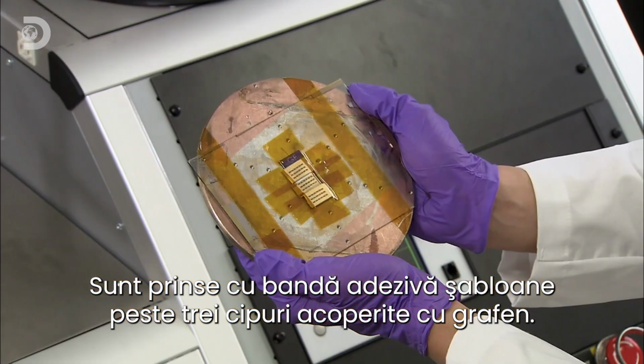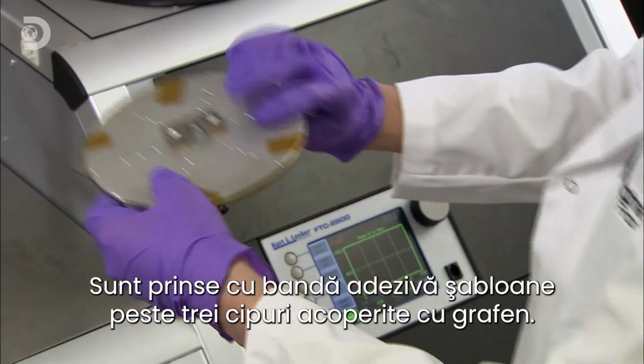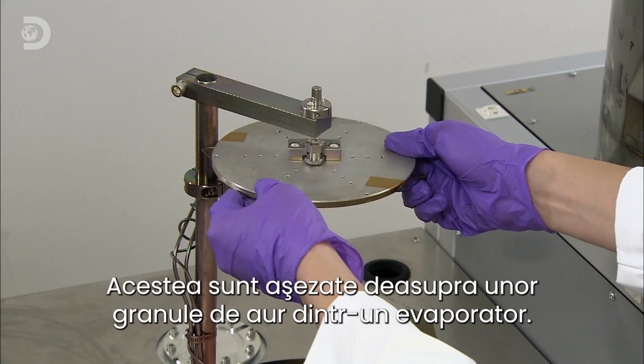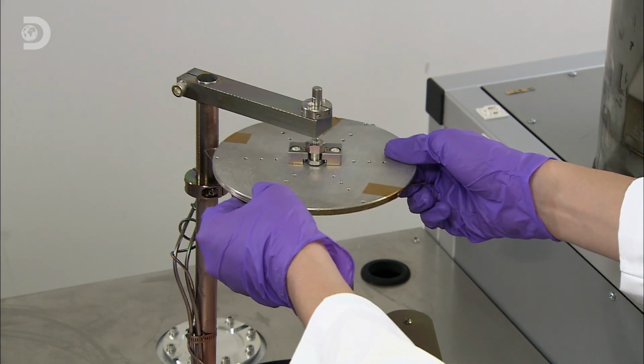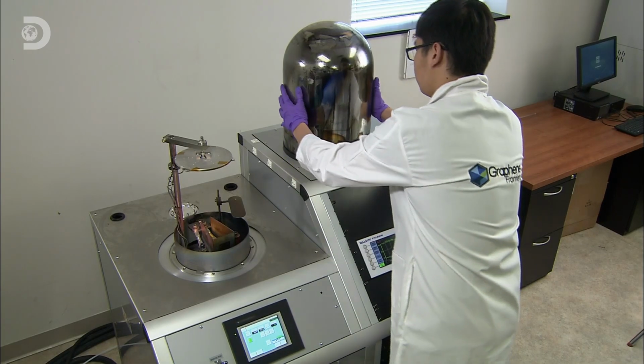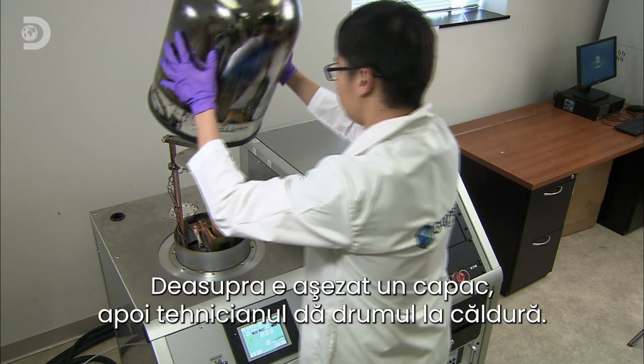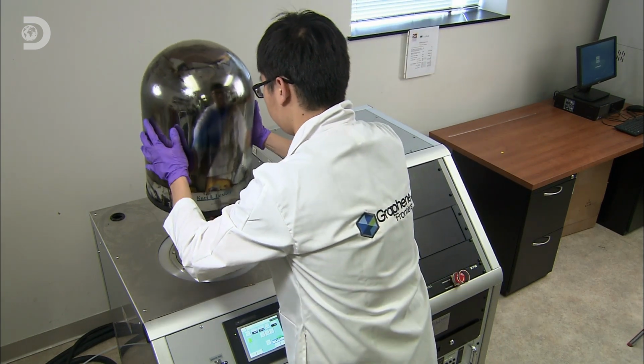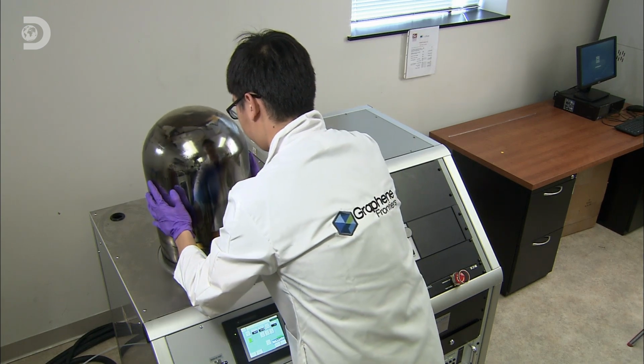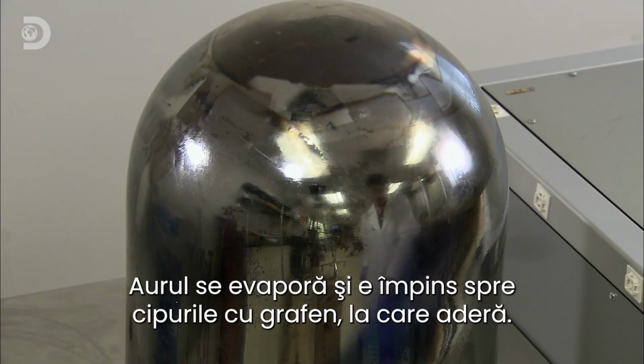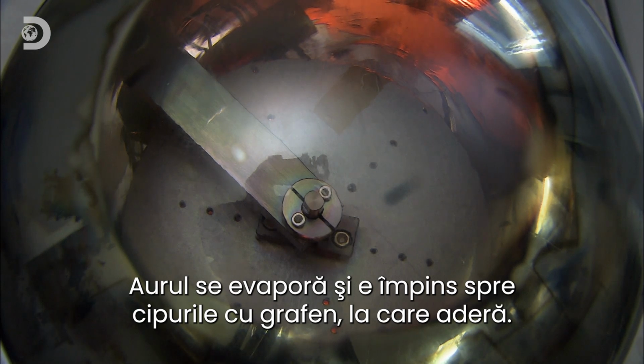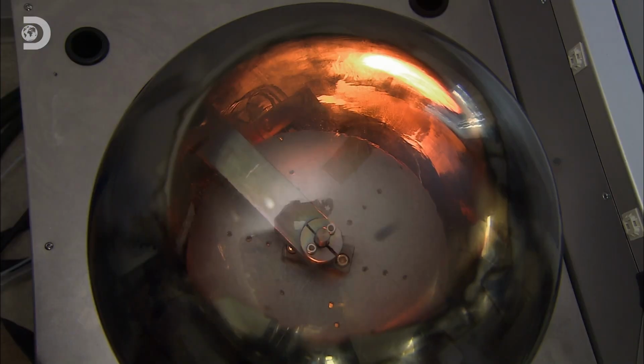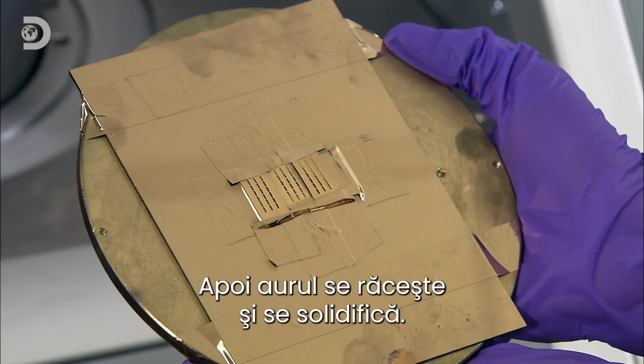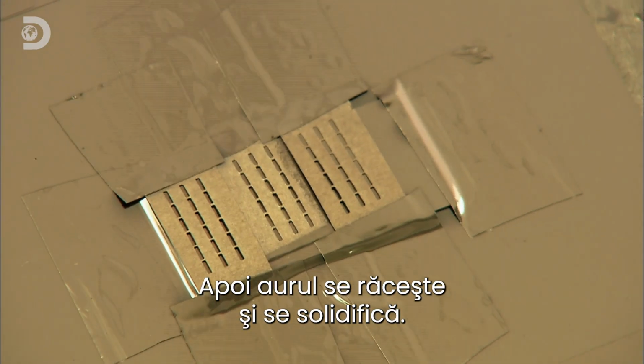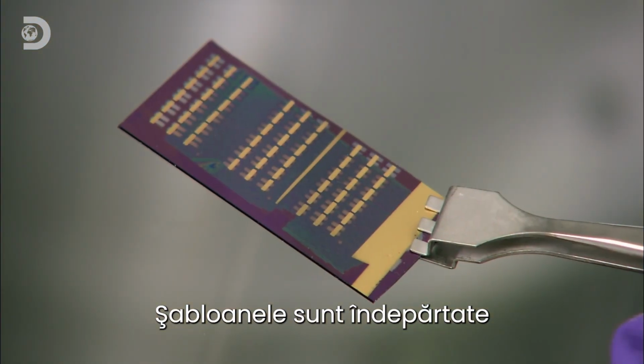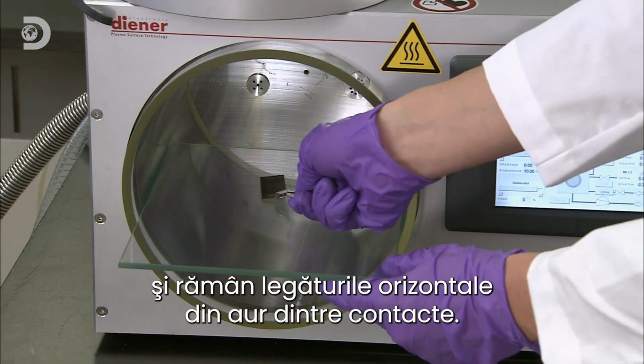After taping metal stencils over 3 of the graphene-covered chips, they're suspended above gold pellets in a machine known as the evaporator. A large bell jar is placed over the evaporator before a technician turns on the heat. As the gold evaporates, a vacuum pulls it to the stencils and the exposed graphene, and it adheres. Then the gold cools and solidifies. The stencils are then removed from the chips, revealing gold horizontal runners between the contacts.